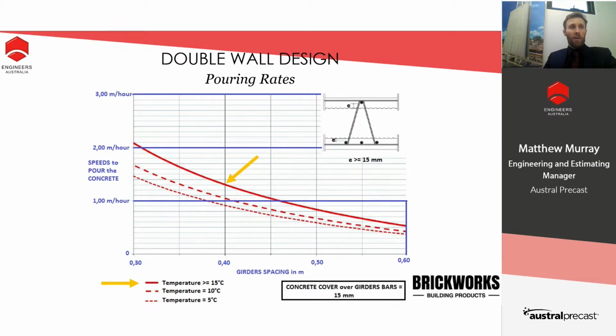So when the shear capacity of the panel is not limited by the girder spacing, the next factor would then be the concreting of the core. For instance, here we can see if we have girder spacing of a 400mm section, we can core fill the double walls reliably at close to 1.4, 1.5 meters per hour. The main thing for this is that the girders require a minimum of 15 millimeters of cover, and we can increase these rates slightly if the cover is increased, but that will all come down to the size of the panel.